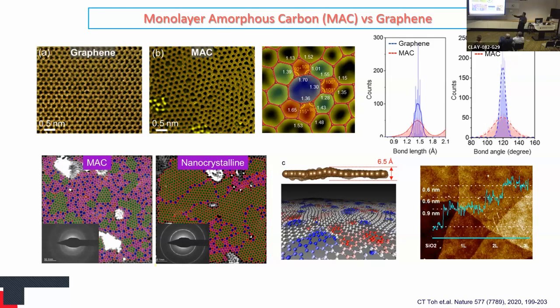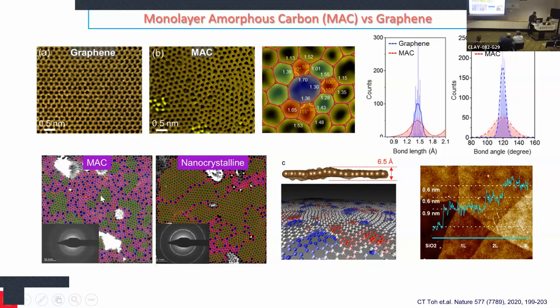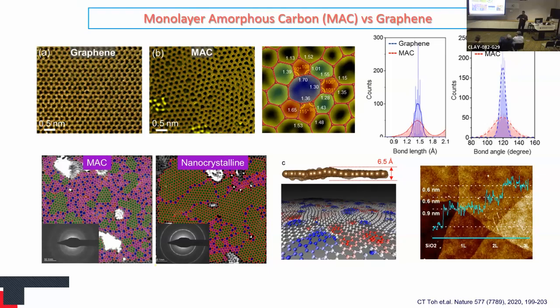There is also a difference between MAC and nanocrystalline material. Interestingly, in MAC you also see very small crystallites. They are still crystallites, but less than 1 nanometer in size, randomly distributed within the matrix of the completely disordered material. Because it is a totally disordered single layer of carbon atoms, it has distortions, and based on these distortions you have different strain fields around it. That also makes it a little thicker than graphene. Graphene is theoretically 0.34 nanometer, or let's say 0.4 nanometer, but here it was around 0.6 nanometer because of the waviness in the material. But still, it sustains itself.